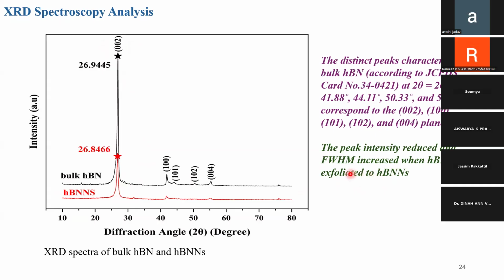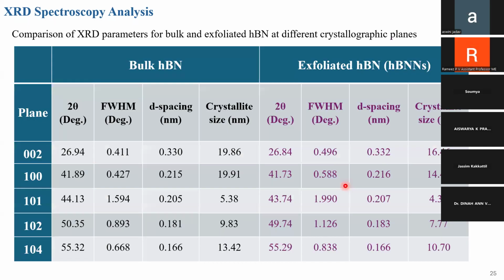So FWHM, or full width half maximum, is increased in the case of HBNNS. So that is another indication of exfoliation. While exfoliating the particles, the peak intensity will decrease and the FWHM will increase. So this is another important thing that you can visualize when you exfoliate it, specifically in XRD.